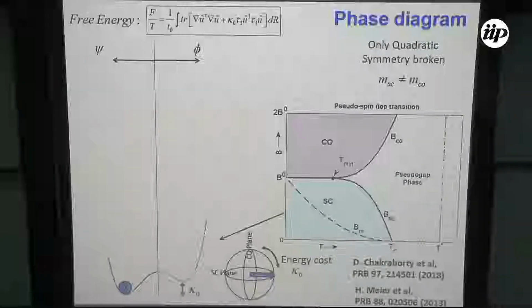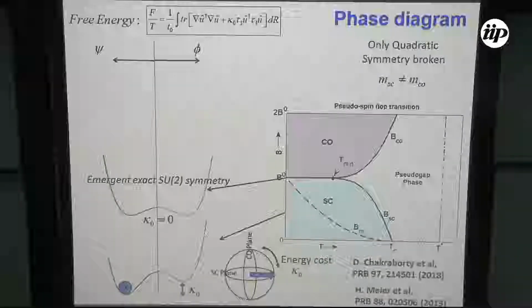Now if we increase the field further, as I told you earlier, the superconducting mass is being renormalized by the field. As we increase the field, the superconducting mass goes higher, and it becomes equal to the charge order mass. So the two free energies, the minima come at the same place, and there is no difference in the energy, and we recover the exact SU2 symmetry exactly at this point.